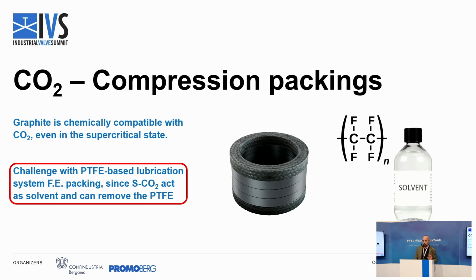Basically, the lubricants that are used in the compression packing industry have a high amount of PTFE in them. The problem is that if we are subjected to supercritical CO2, we can have this solvent action, and the PTFE can be removed from the compression packing, and this will cause two effects. We will start to have higher leakage because of the voids that we will have in the compression packing because of the PTFE that is removed, and we will have higher friction between the rings and the stem.